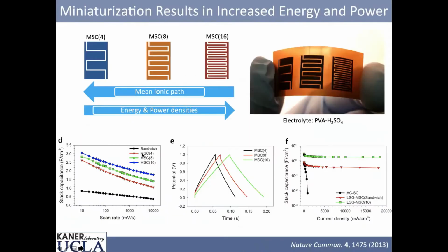Okay, how are these going to work? Well, we did some with 4 interdigitated, 8, and 16. And of course, the more you do, the closer together they are, the better they are. They're flat, and you just put a drop of electrolyte. If you look at the stack capacitance, as you go to 16, you get really good capacitance. These are the charge-discharge curves. There's low internal resistance, a little tiny IR drop. But the stack capacitance is very good, and these work out at 20,000 milliamps per cubic centimeter.